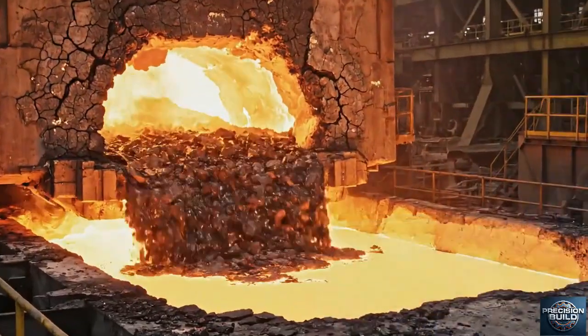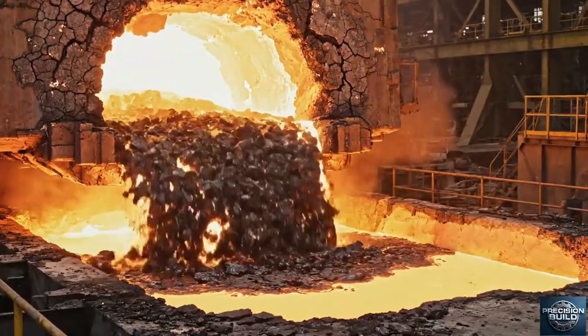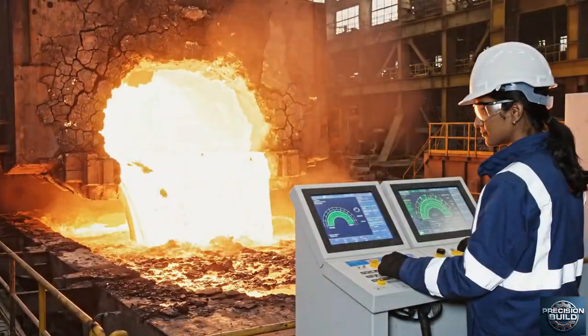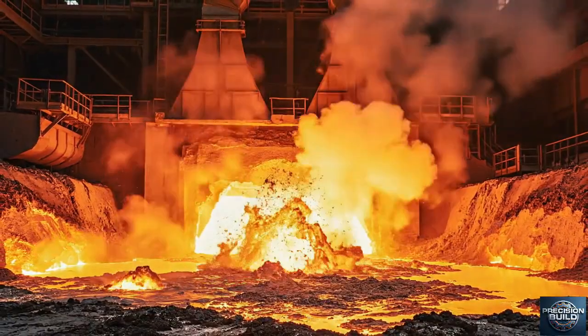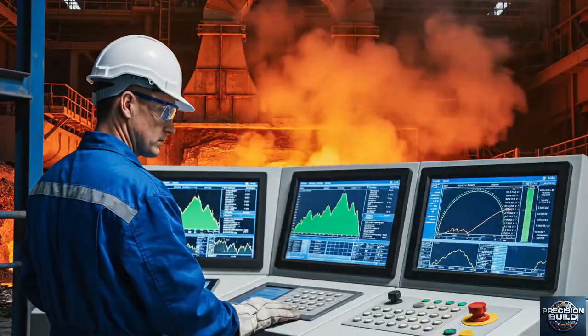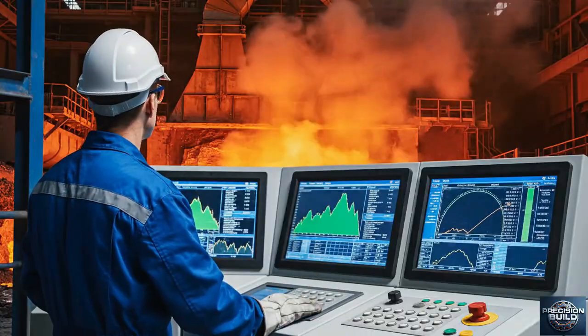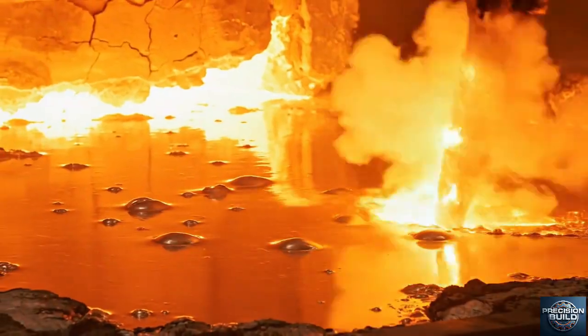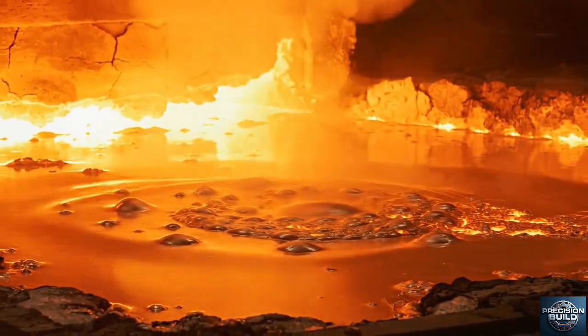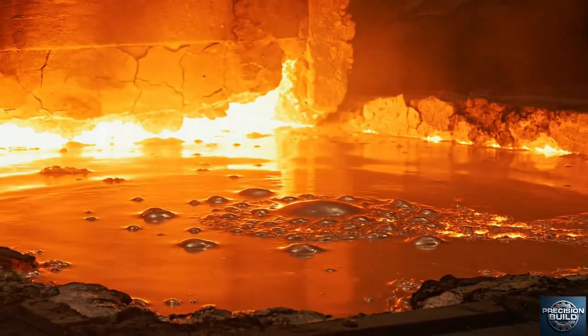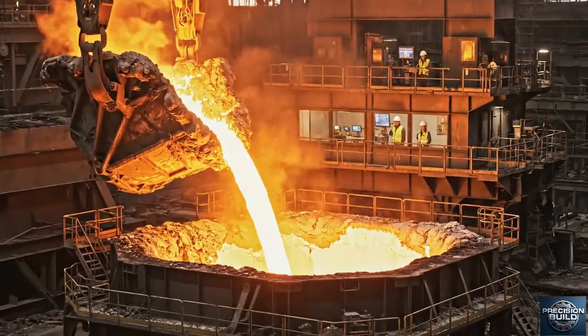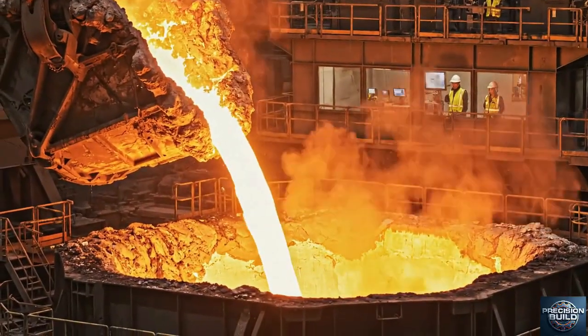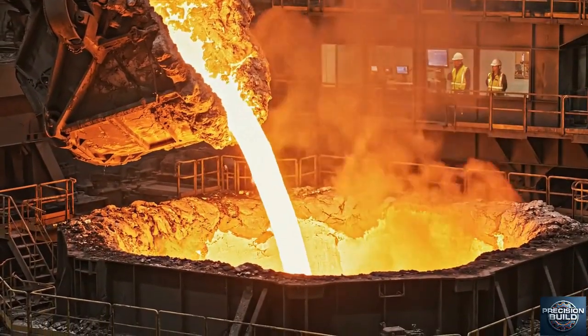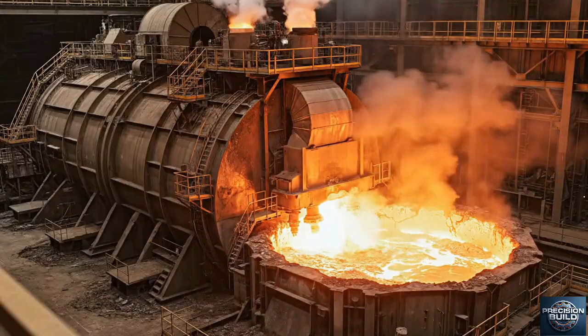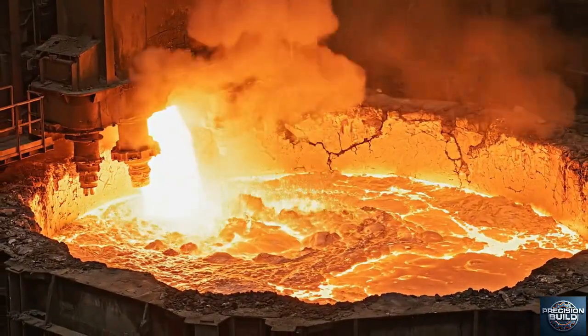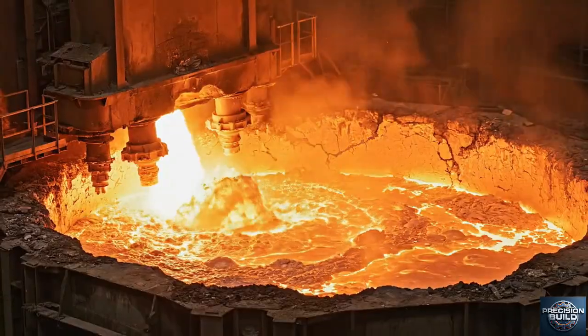Iron impurities oxidize and form slag, which separates and rises above the molten copper for removal. Blister copper forms as impurities are removed, leaving molten metal with high copper concentration. Molten blister copper is charged into converters for final refining and impurity removal stages. Air blowing accelerates oxidation, removing remaining impurities and refining molten copper to higher purity.